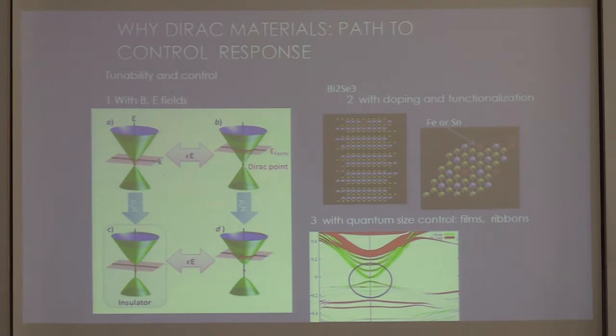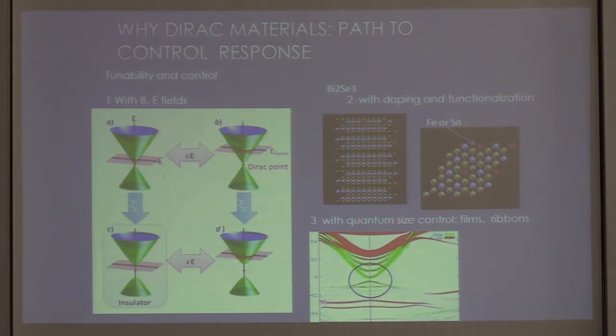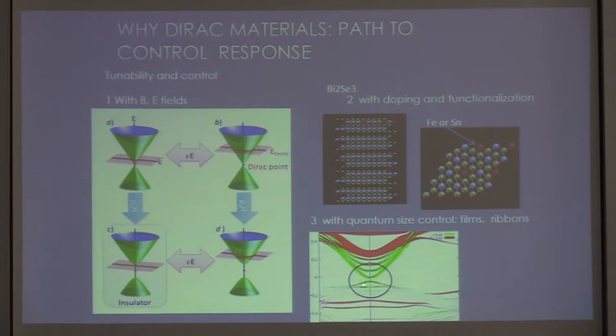Obviously the Dirac point is interesting, and we already see this evolution of the field in graphene where a lot of effort goes into functionalizing graphene and developing interesting applications based on the nodal point. You can apply external fields to move the chemical potential, apply magnetic fields to open gaps, put dopant atoms to induce non-trivial behavior — as in the case of magnetic impurities in topological insulators — or you can functionalize it by placing the Dirac node into a restricted geometry, for instance a ribbon, where finite-size quantization leads to interesting effects. What's shown here is the splitting of the Dirac cone in about a quintuple layer of bismuth selenide, where you have five layers with an open gap.